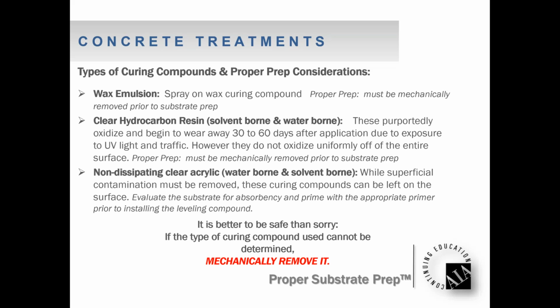That may be the case in the middle of the slab where the sun's hitting it and where everybody's walking, but over next to the wall where the sun isn't hitting it, nobody's walking, you still may have a curing compound there. So the bottom line with these dissipating curing compounds, they're actually the most dangerous ones out there from a bonding standpoint, because you don't know if they're there or not, due to traffic, due to ultraviolet light, things like that. So with regard to these clear hydrocarbon resin dissipating curing compounds, we always say to mechanically remove those down to clean concrete.